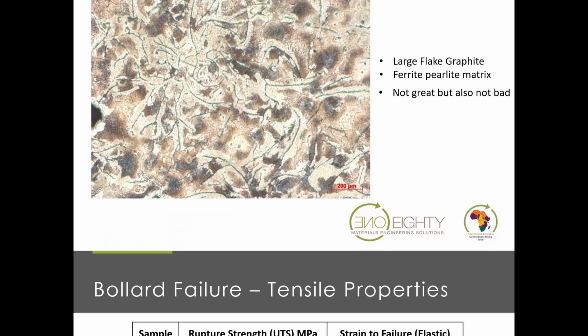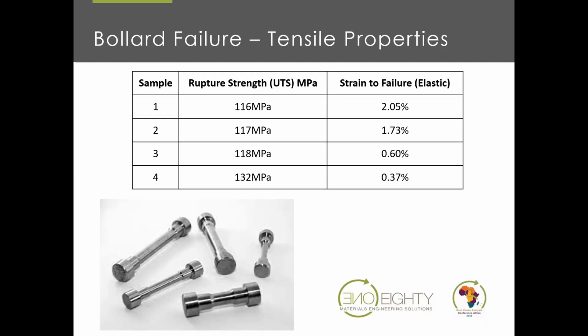We then looked at the tensile properties, machined out a few tensile test specimens according to the standard for cast iron. And as you can see, we got an ultimate tensile strength. That means the load at which it fails when you pull it apart. And what's important to notice is the strain to failure. So that's the amount by which you can pull it before it breaks.